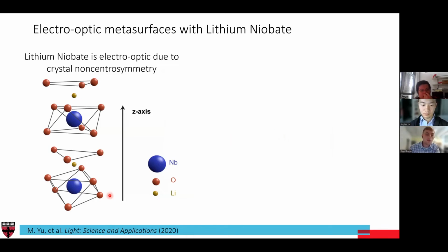In here, in red, we have these oxygen atoms that form a hexagonal crystal structure. And inside the octahedral interstitial sites of this lattice, we have alternating layers of lithium and niobium. So niobium is this very large blue, and lithium is this smaller yellow. And actually, what is maybe quite important about this is that the relative position of the niobium and lithium atoms is not exactly within the center of that interstitial site.